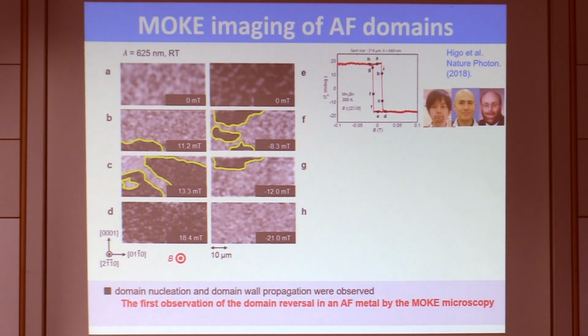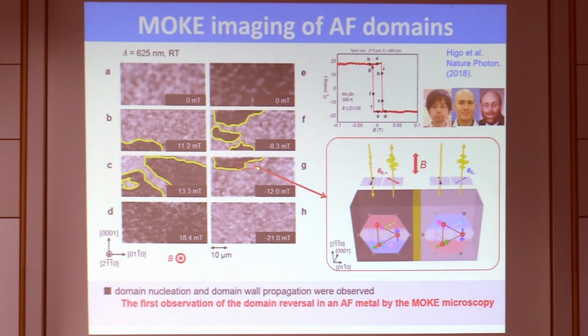I only show the Kerr effect here. This is the Kerr effect as a function of field. You can see a very sharp change, and as a function of field, it changes sign, for negative and positive field and positive and negative field. The black one corresponds to the negative sign of the Kerr effect. As you increase the magnetic field, this black domain becomes dominant, and vice versa. So there is clearly a domain wall separating these magnetic octupole domains.